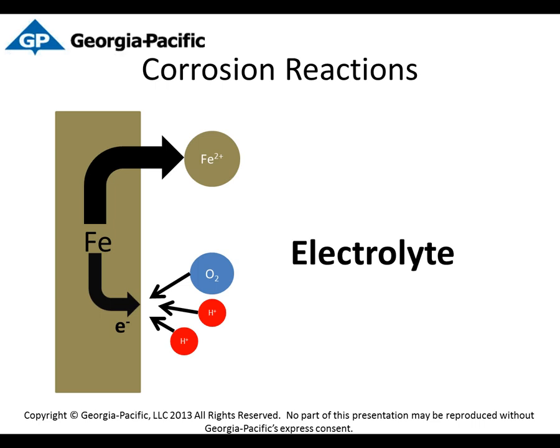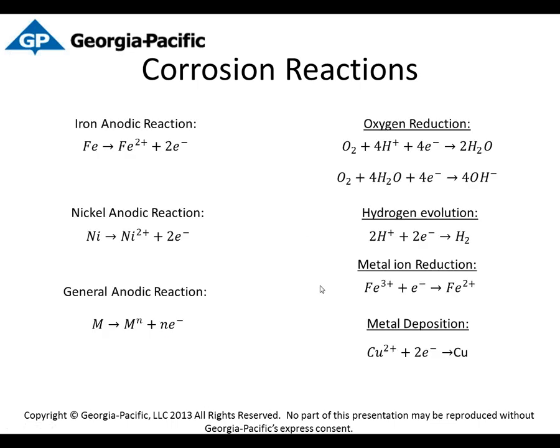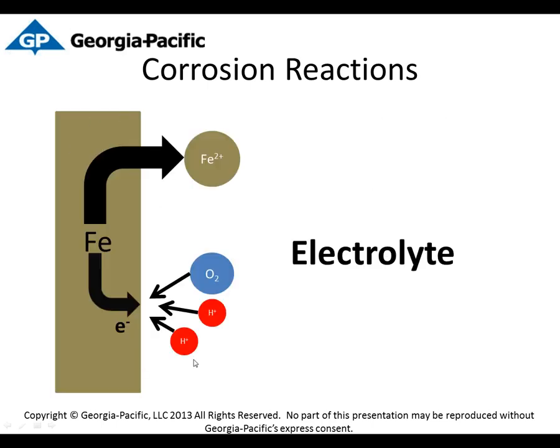So just again, another look at the corrosion reaction. If you have an iron bar and an electrolyte, the anode is giving off the iron ion. The electron is passing through the iron into the cathodic site. The electron can meet either a hydrogen or oxygen atom to complete one of these cathodic reactions, either oxygen reduction or hydrogen evolution, depending on the pH of the solution. That's just a real basic overview of a corrosion cell.